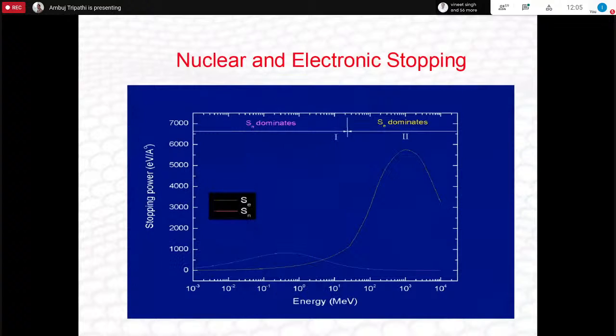This is again a very common curve which we always show. All you have to see is that on the top two regions are written, Sn dominates, Se dominates. And if you look at the energy scale, it says somewhere around 1 or 10 MeV, up to where you see the purple curve, which rises. So that gives the nuclear energy loss. It rises up to something around a few MeV, and then it starts going down. And electronic energy loss, shown here as Se, E for electronic, starts increasing somewhere around 10 MeV or so, and this will reach a peak in the range of hundreds of MeV.